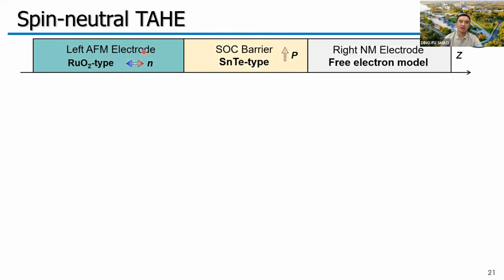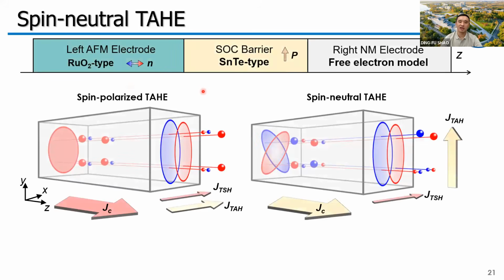Next, we change the left electrode to a ruthenium oxide type antiferromagnetic metal. As we mentioned previously, ruthenium oxide can support spin neutral currents with momentum-dependent spin polarization for the electrons. So we can match the conductive channel of ruthenium oxide and the distribution of the spin filtering factor in the barrier to find out what the distribution of the transmission is.